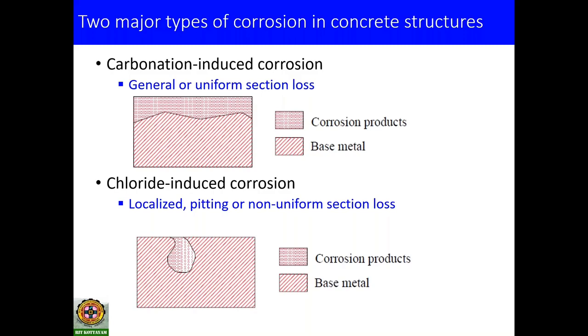the depassivation of the passive film can happen. And it's a regenerating process. If you see the reaction, it will form FeCl2 and it gets split again into Fe2+ and Cl-. So it's a regenerating process. Because of this regeneration, you can see a localized corrosion, or what we call pitting corrosion, in the chloride induced corrosion category. We will have a non-uniform section loss in the case of chloride induced corrosion, whereas it will be uniform section loss in the case of carbonation induced corrosion.